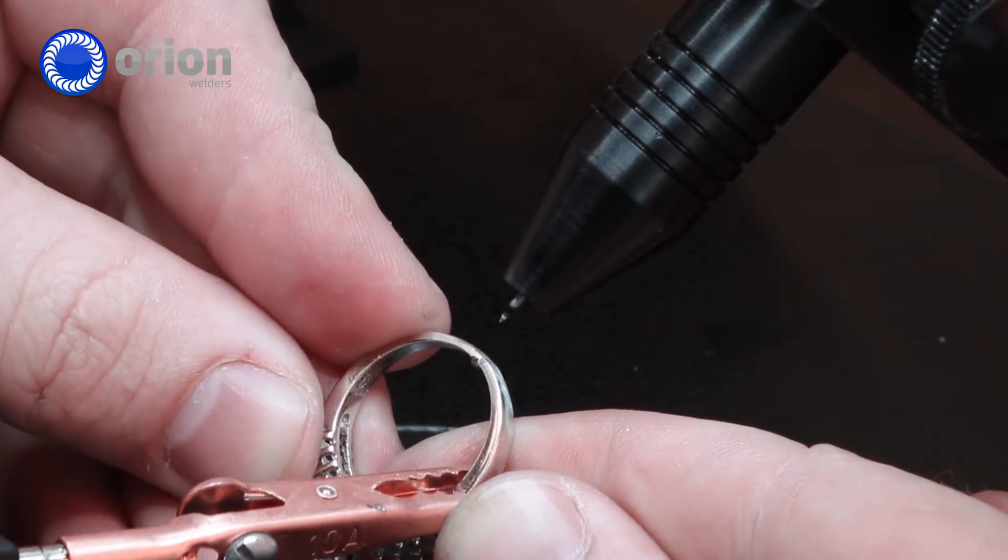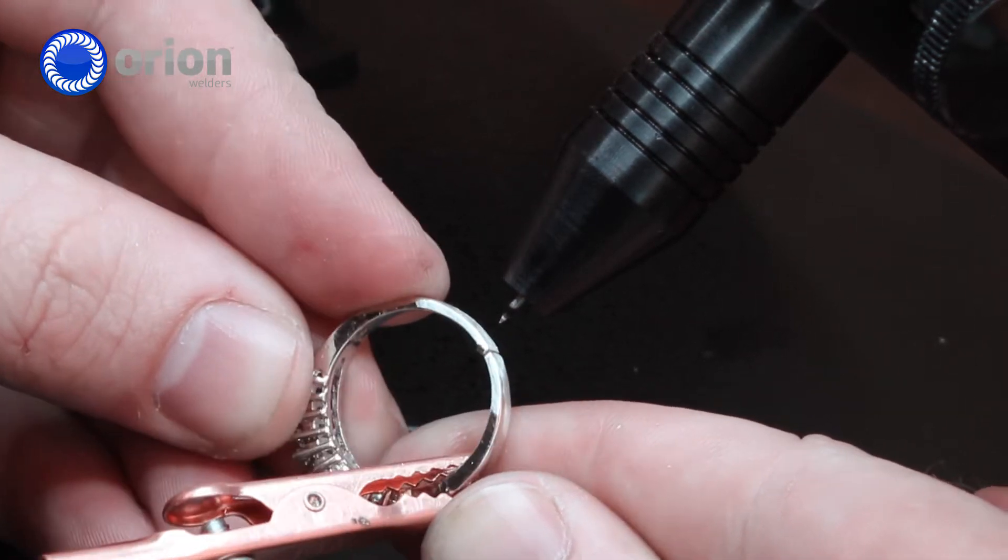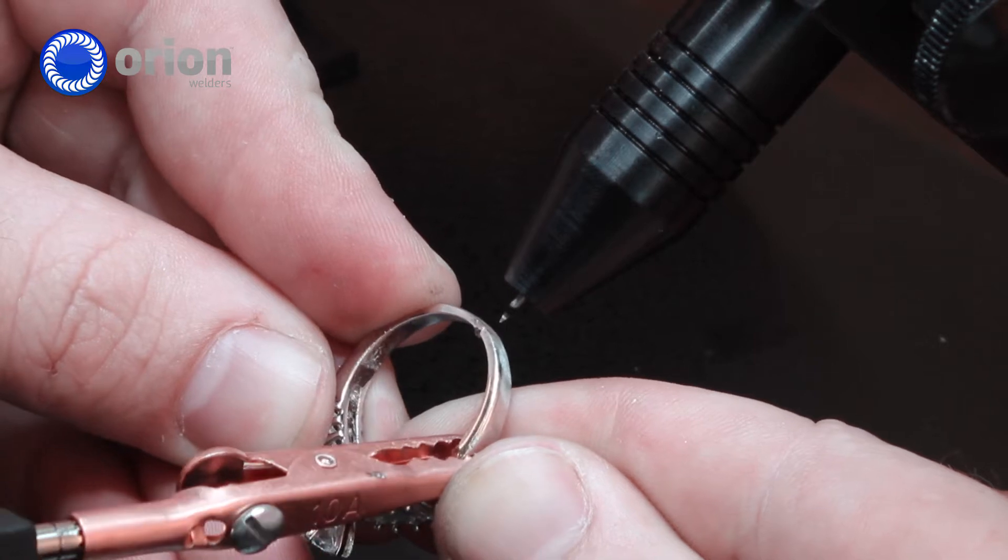I'm at 19 watt seconds of energy. I'm going to push the piece together so you see the gap there. I push it together so that the pieces are contacting.